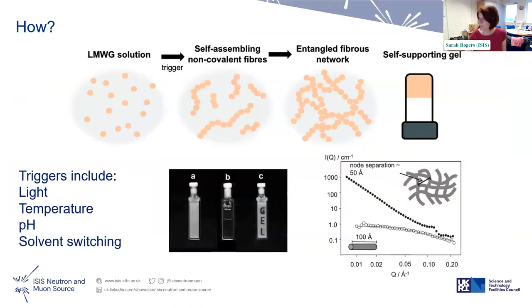So how do they work? You normally take a solution of those molecules, as I showed you earlier. There's a trigger, so that can be light-induced, temperature, pH, or even solvent switching. That then forms this self-assembling of non-covalent fibers, and then eventually they form entangled fibrous networks, and you have a supporting gel. So the example I show you there is just where it was a light triggering one.